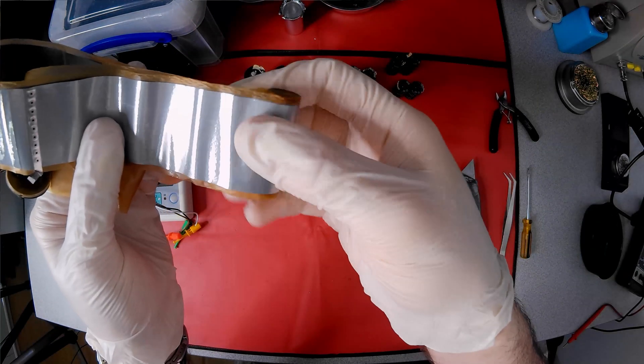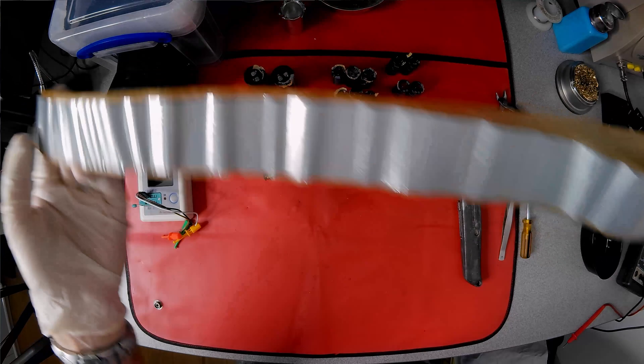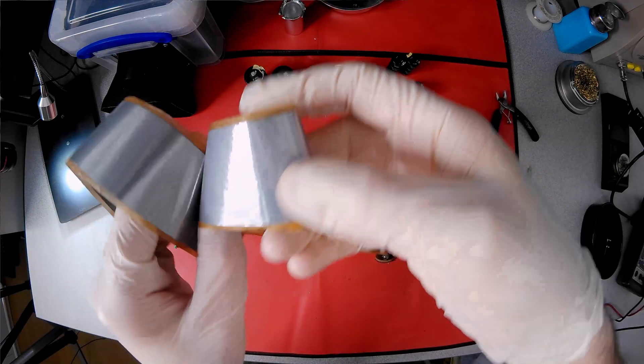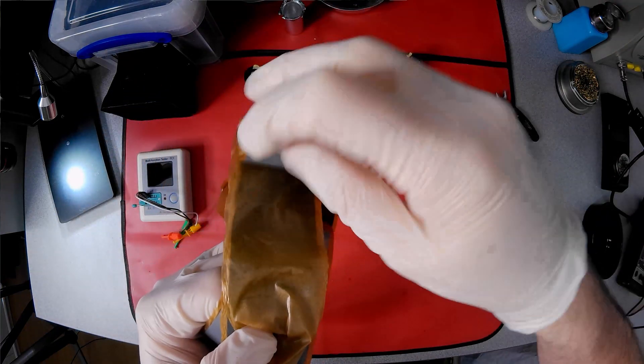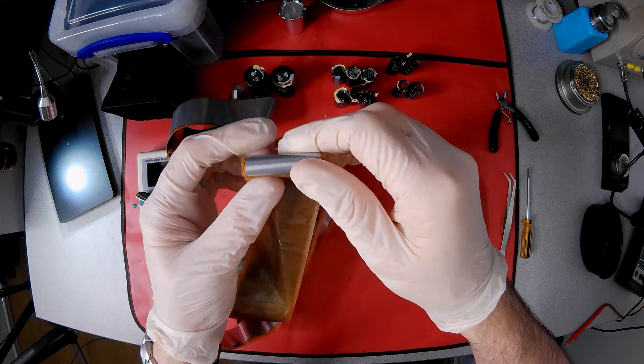The brown layers are paper impregnated with the electrolyte liquid. It is believed that an incomplete stolen formula for electrolyte caused the capacitor plague of the early 2000s. It corroded the aluminium, creating a gas that caused them to burst. These predate that time and are from a reputable manufacturer, and I see no evidence of corrosion.